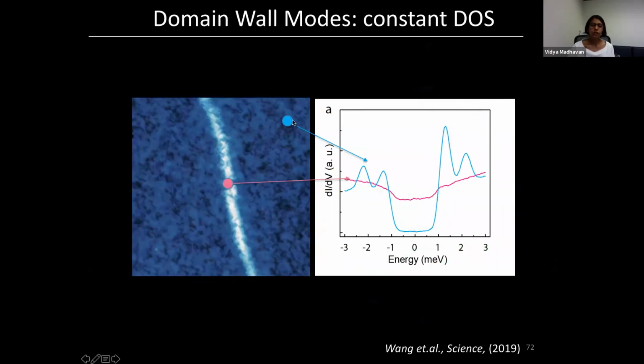So now you can measure the dI/dV spectrum far away from this domain wall, and it's this blue spectrum here. And if you go right to the domain wall, this is what you see. You don't see the huge peak that we saw before in the vortex core. Instead, you see this flat density of states. This is a finite density of states, meaning inside the superconducting gap you have a whole bunch of states filling up the superconducting gap. The superconducting gap still exists. You can see it go down, but there's an extra density of states filling up the entire gap from one end to the other, okay?